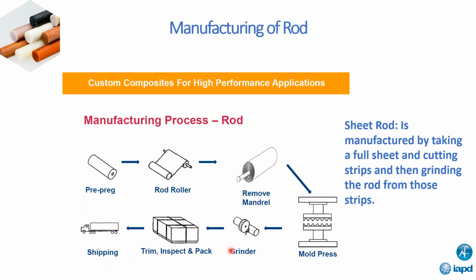So rod. There's two types of rod out there. There's the molded rod, and then there's the sheet rod. The molded rod in the example here is basically the same type of process. You take that pre-preg material, the resin, the cloth, you wrap it around the mandrel, roll it up, and then prior to that heat and pressure process, you remove the mandrel, stick it in the press, and then crunch it down, and then grind it out at the end. That's a simplified version of how molded rod is manufactured.